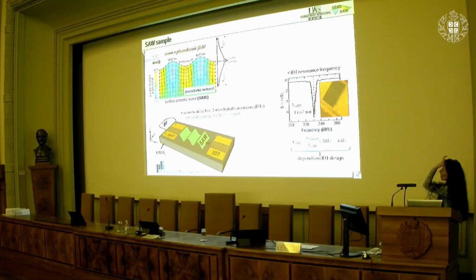So in order to manipulate our nanowires, we use so-called acoustic waves. We actually use the strain and the piezoelectric field of this acoustic wave that propagates along the surface of a strongly piezoelectric material. In this case, we use the so-called acoustic delay line, which consists of two metallic interdigital transducers that were lithographically patterned on a lithium niobate crystal.